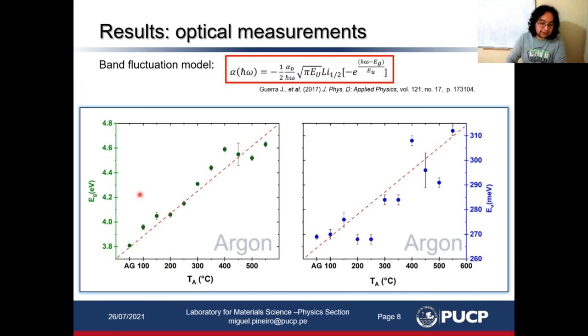Now, this figure shows the energy—the left figure shows the band gap energy and the right figure shows the Urbach energy, both as a function of annealing temperature. They were calculated using band gap models. We can see in the left figure that the widening of the energy band gap can be caused by the Burstein-Moss effect and is related to increasing carrier density.